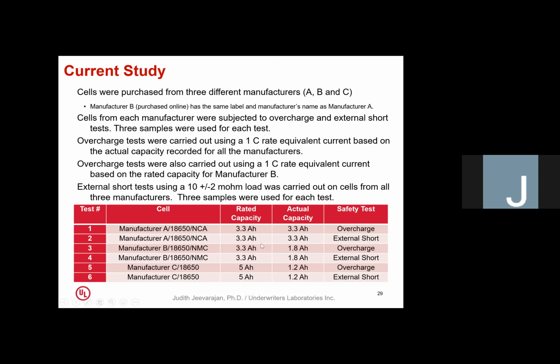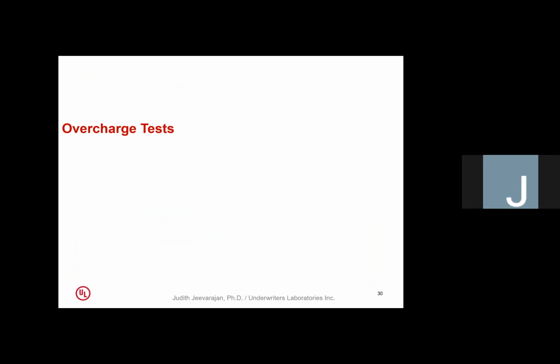As you can see from the capacity checks, with manufacturer A, obviously, the rated capacity and our measured capacities were the same. With manufacturer B, we got only 1.8 amp hour capacity, even though they labeled their cell as 3.3 amp hours. And with manufacturer C, it was even worse. Even though they labeled it as 5 amp hours, we got only 1.2 amp hours. And as you can see, we did overcharge and external short tests on them.